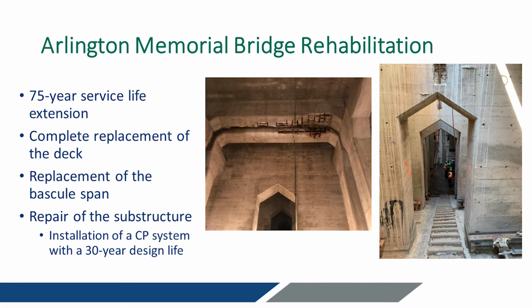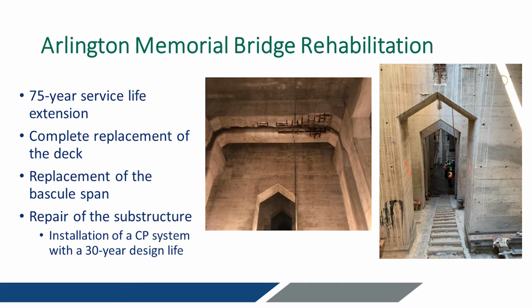The structure was going through a 75-year service life extension. As part of that, they did a complete deck replacement, and they used stainless steel for the deck. The bascule span that I mentioned was completely replaced because it no longer needs to open, so they just have a steel span there. But the substructure, the arches and the cross walls, all needed to be rehabilitated due to corrosion deterioration.